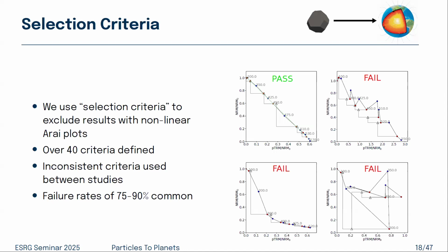Things get much more challenging as you go further back in time because things have much more difficult histories to reconstruct and more things have happened to those rocks. There's also been some discovery of some effects that are time dependent. There's a study that I was on in 2021 where we showed that if you leave these things in a field for 5 years and then measure them again, do the experiment again, you find that the curvature has increased. So there are some temporal effects. So maybe it's possible that this is more of a problem for things that are older than things that are younger, but that is, again, very hard to test.